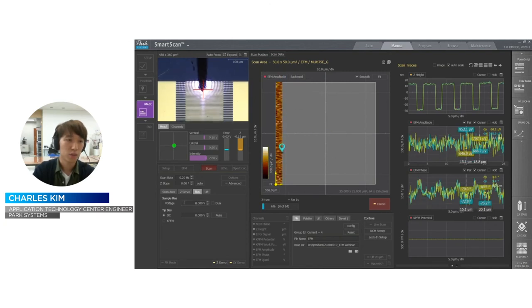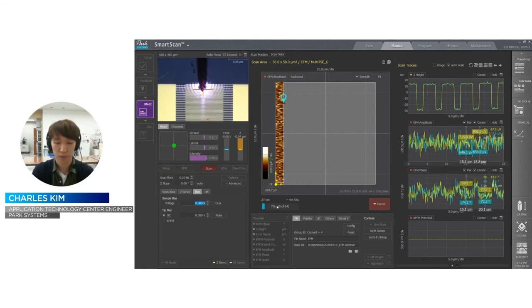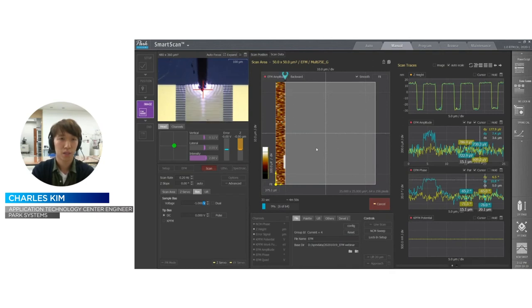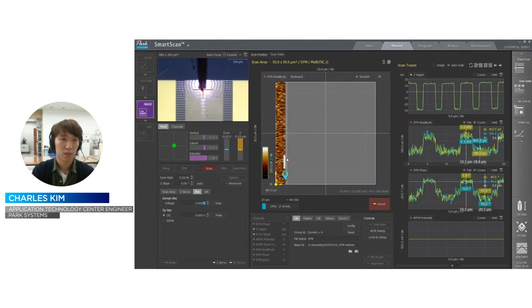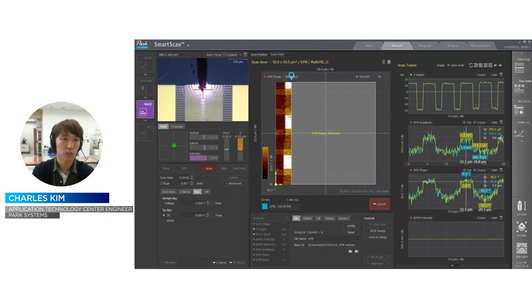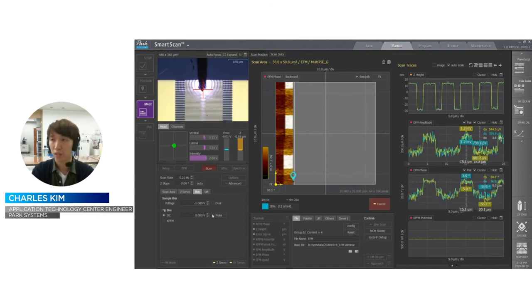And during the measurement, if I change the sample bias to 0.5, then one by one different electrodes show a higher amplitude signal. And if I see the EFM phase, you can also see the differences because the potential is changing now.